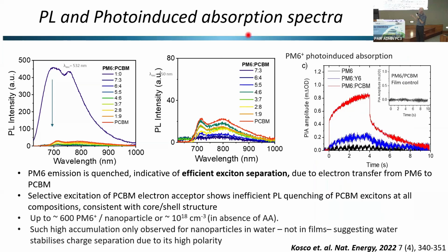And if we look to see what's happening here, one of the important things is, if you look at this PIA spectra, you'll see that you get this charge generation. So this is the PM6 polarons. And once you stop the irradiation, these charges persist over a time scale of seconds. So we are able to really access chemistry. Organic chemistry occurs at that time scale. If the lifetime of your charges is on a microsecond scale, you're not going to be able to do a lot of chemistry with this.